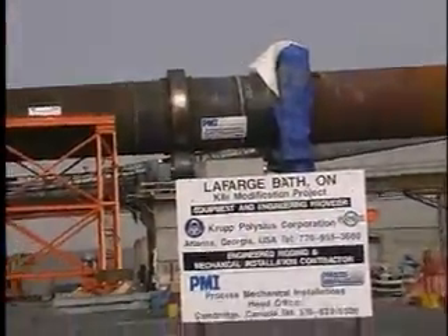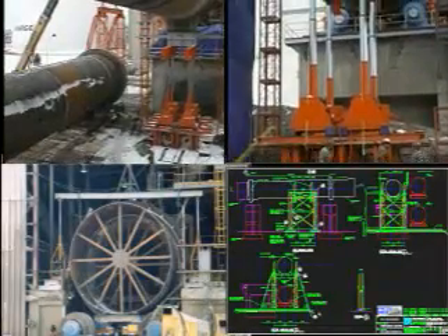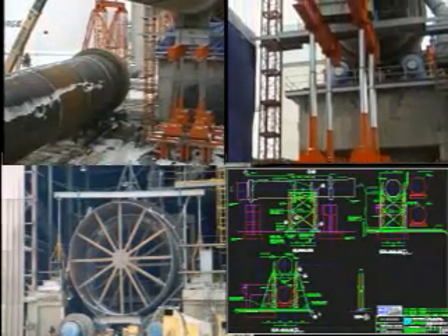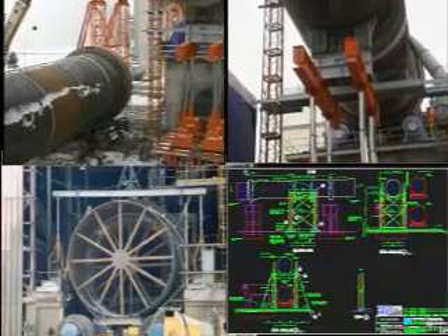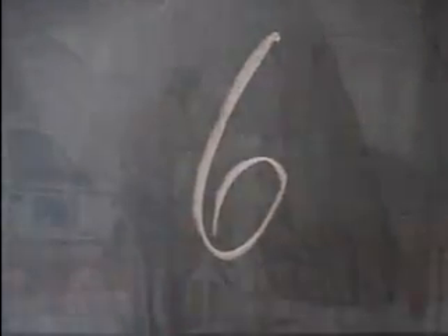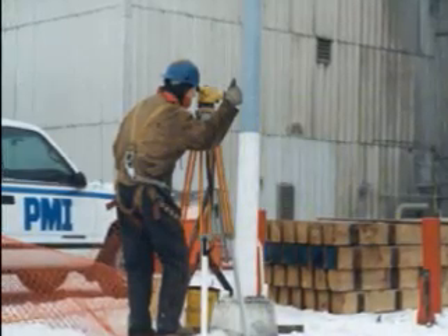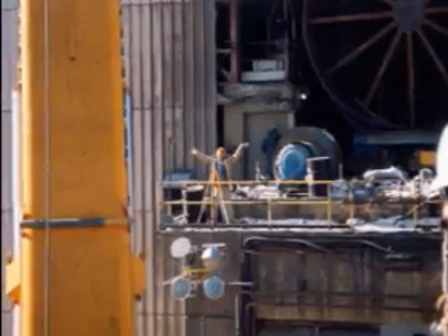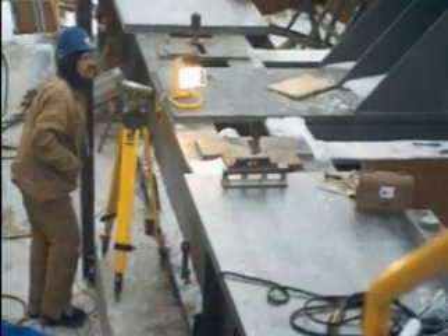3. Kiln pre-assembly handling methods and welding procedures were engineered to satisfy submerged arc welding process requirements in the field. 4. All welding operations were performed at controlled preheat temperatures under weather protection enclosures, and no weld failures were detected by NDE testing. 5. Hydraulic skidder, crane, hydraulic gantry and tower strand jack lifts were fully engineered and certified prior to execution. 6. Work was performed during Canadian winter conditions involving over 1,000 man-hours of engineering and planning and over 18,000 direct labor man-hours of effort, and was completed with no accidents or incidents.